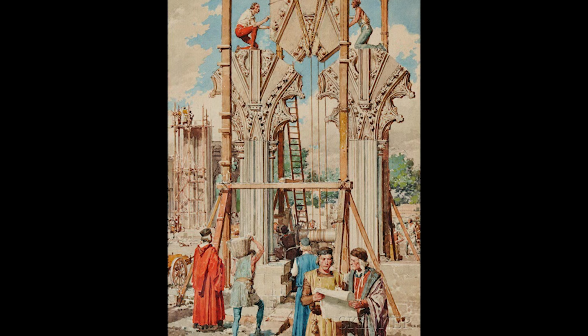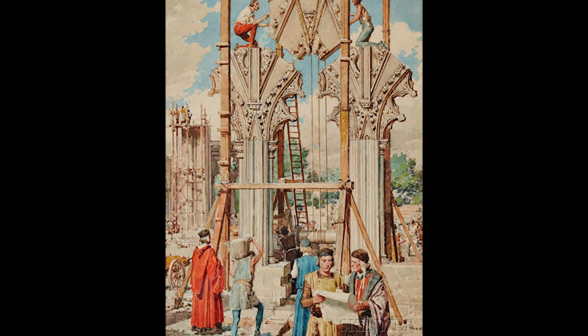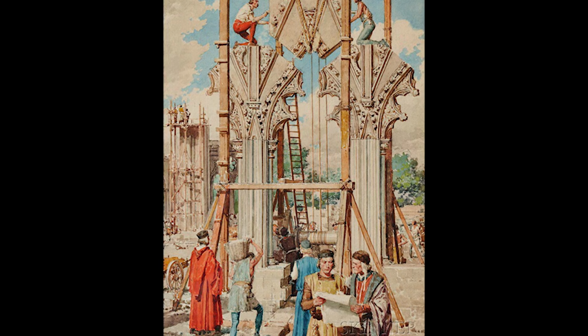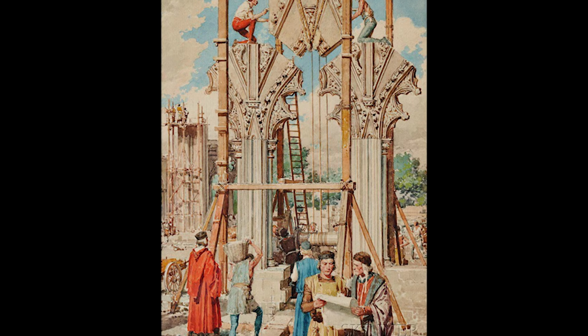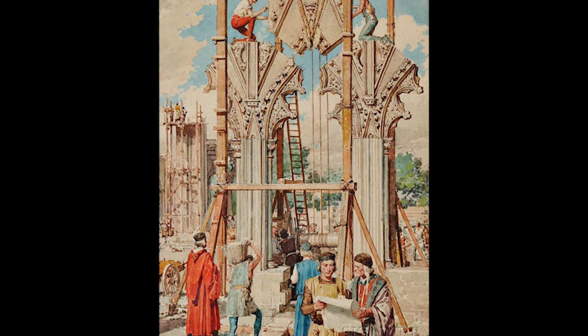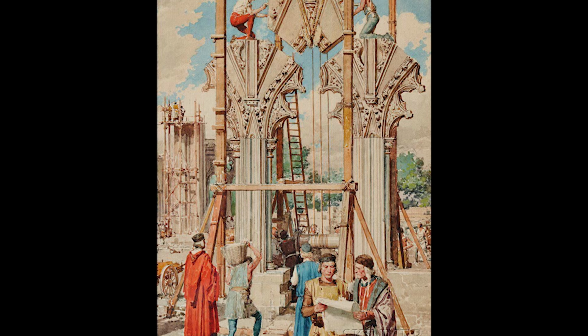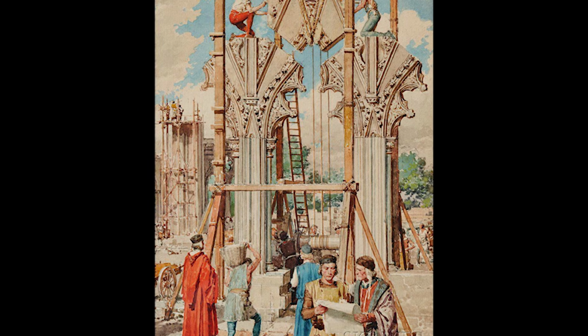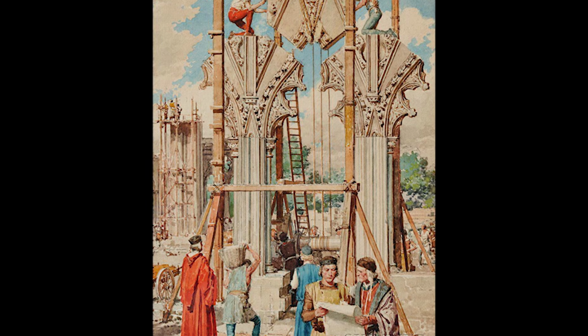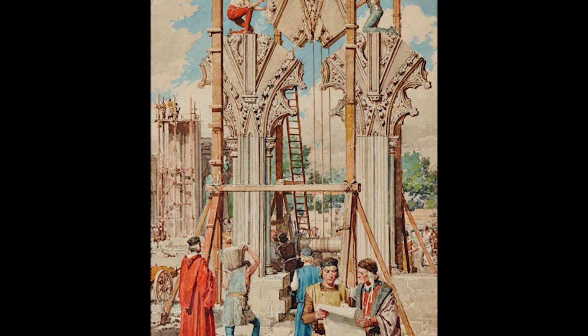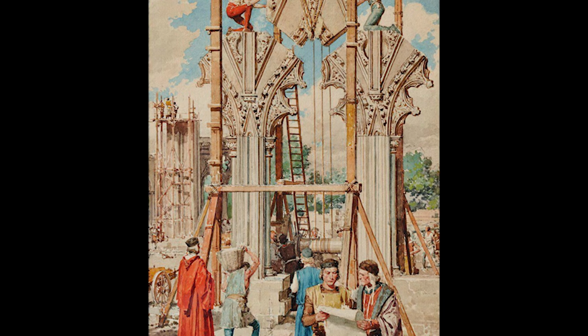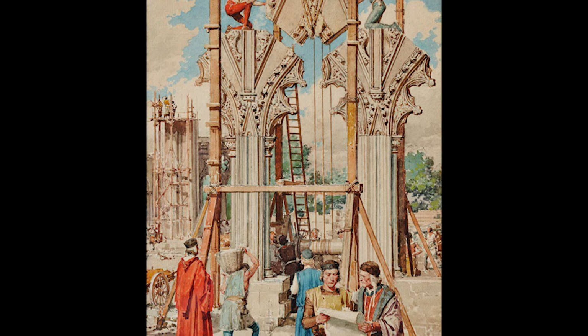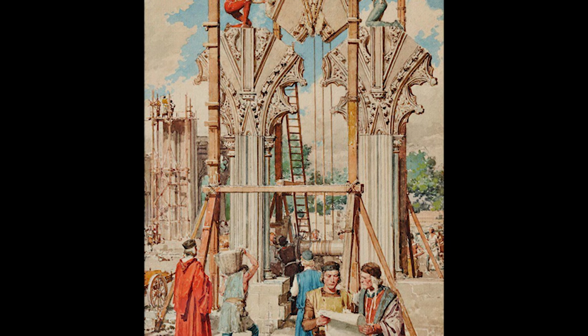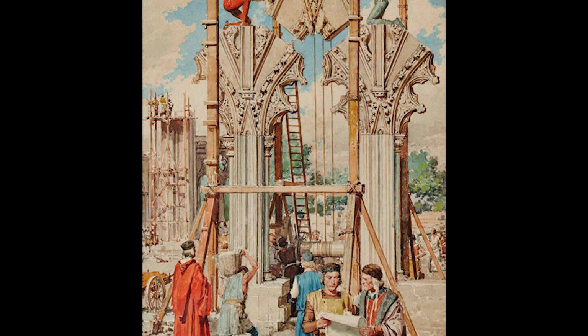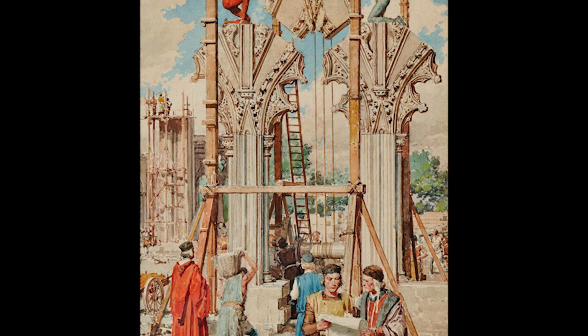More importantly, no loss of bond occurs between the lime mortar and bricks, even where joints have opened and closed repeatedly. The Portland cement mortar shows different behavior that reveals its fundamental rigidity. Initial movement cycles produce no visible change, with the cement mortar resisting deformation through its superior compressive strength. However, stress concentrates at specific points rather than distributing evenly through the mortar system.